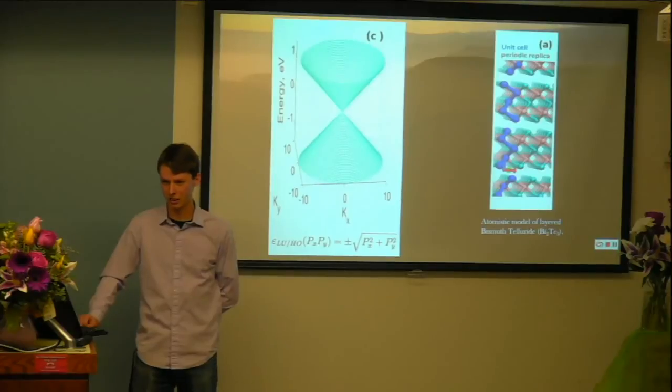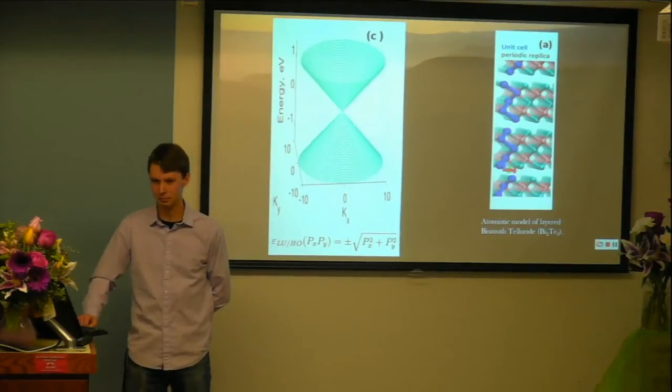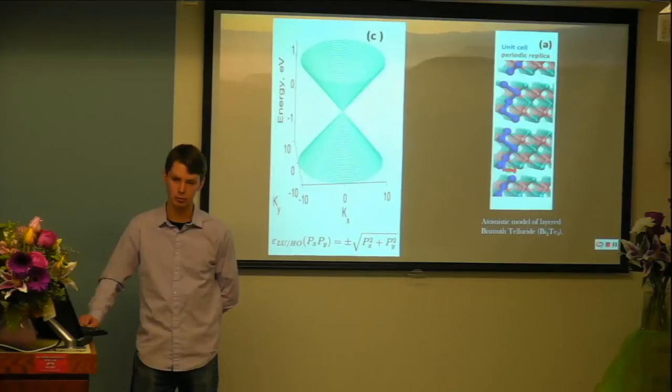But there are of course more than one material like that. And technically, computational chemistry was applied to create predictions or a database. They tried to go through many variations of possible semiconductors, multiple combinations of metals and non-metals, calculating the electronic structure, the dependence of energy on the K points, and checking whether you can get Dirac materials or not. And we found about hundreds of materials as predicted. Some of them are not synthesized yet.